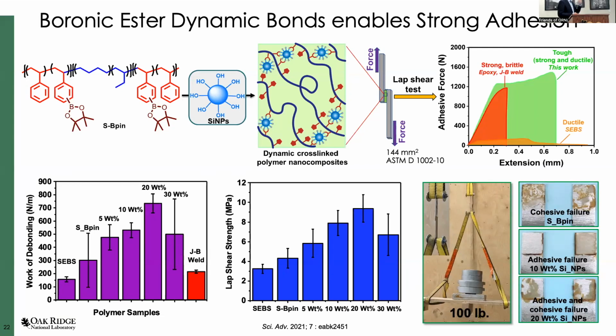This was semi-accidental that we found, because a staff member, Anis Roman, was doing this on the glass. He told me he could not take it out. It sticks so strongly. So we started looking at the adhesion properties. This is again the starting material. We functionalize it, and it goes up a little bit, and then with nanoparticle addition it gets much stronger. This is the strength and also the lack of debonding. Showing a picture here, this is about a 1 centimeter area, and that area can hang a very heavy load, something like 100 pounds. You can see it can hang very nicely. We apply heat and it sticks. That was something interesting we found.